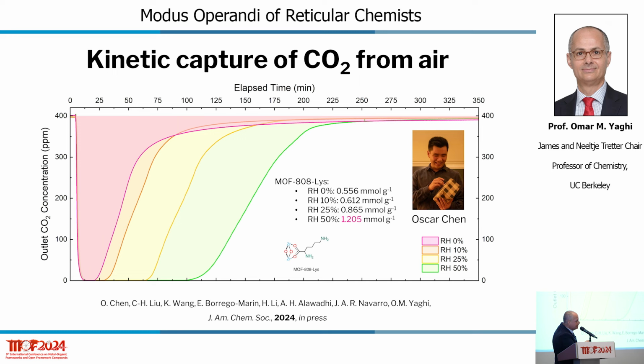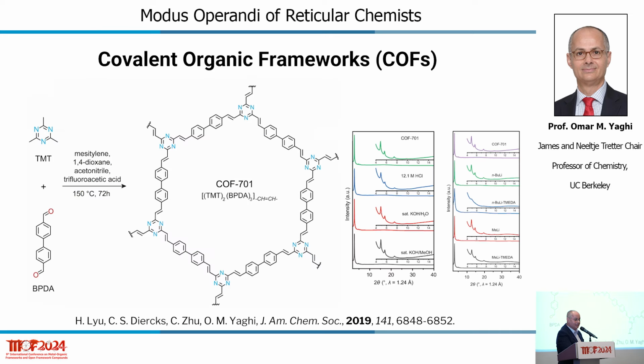It's 1.2 millimole per gram. And the theoretical studies tell us that that's okay as long as you can cycle 100,000 cycles. But this material can't. Did you hear me in the back? And so we scaled up this material to a kilogram quantity, and we built a machine, a prototype, and we cycled 500 times. And it breaks down because although it's stable in water and acid, it's not stable in base. And that's why we were preparing for this in terms of the basic chemistry.